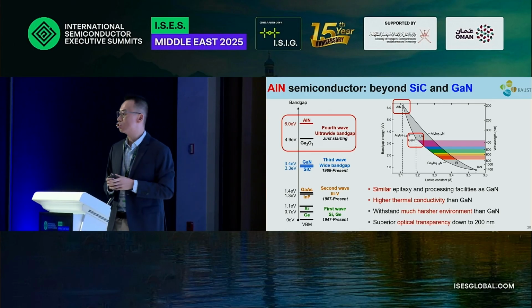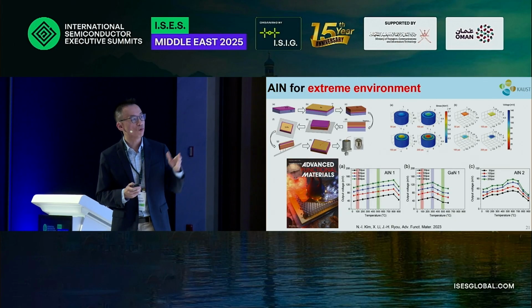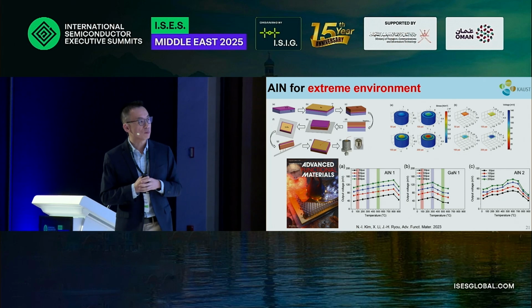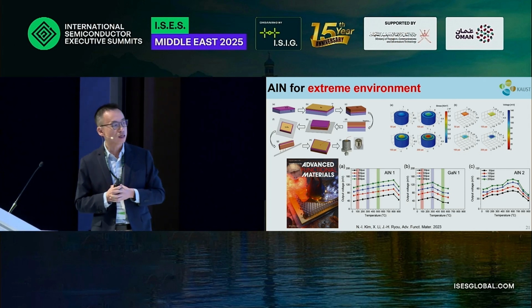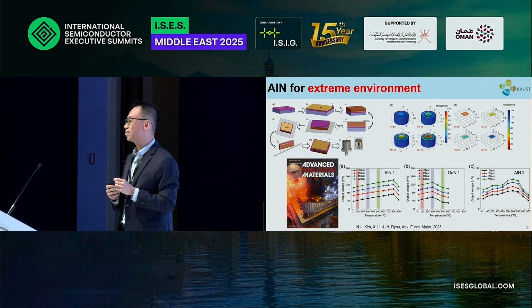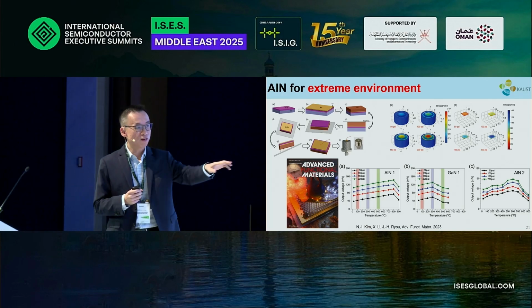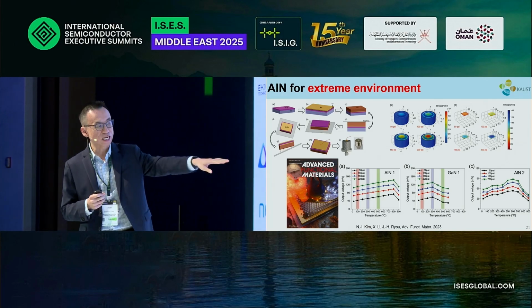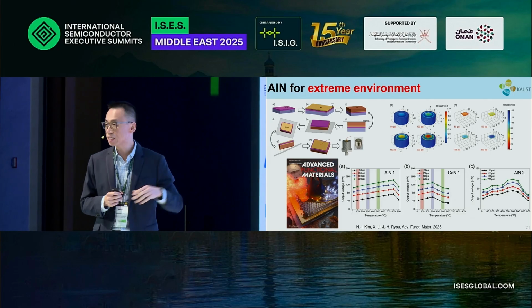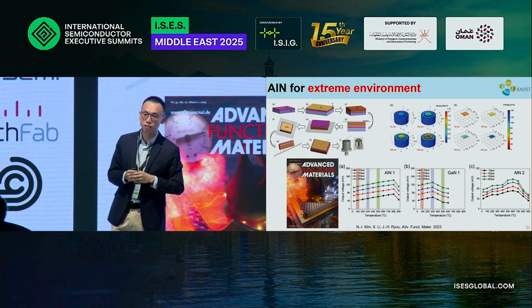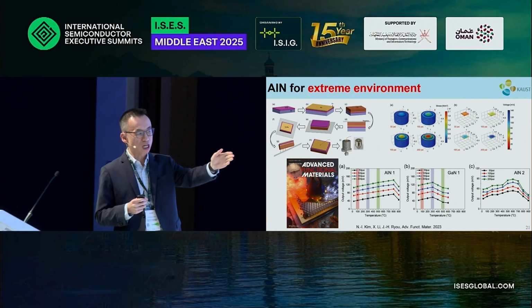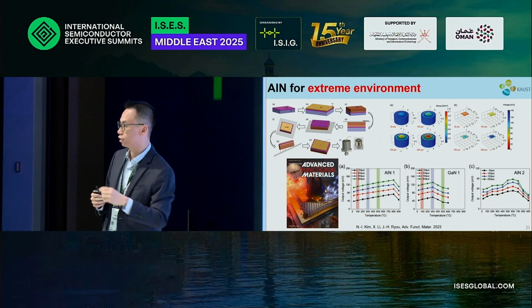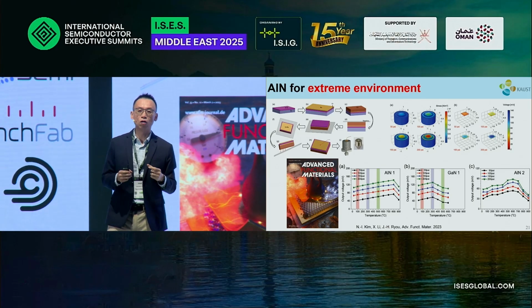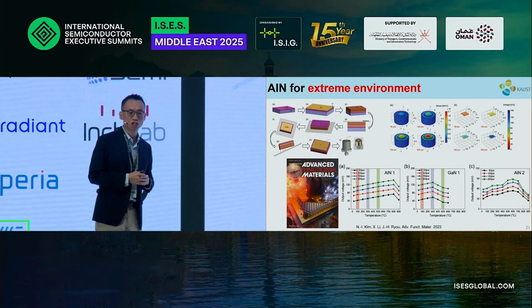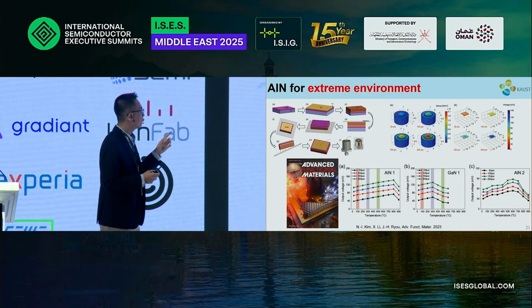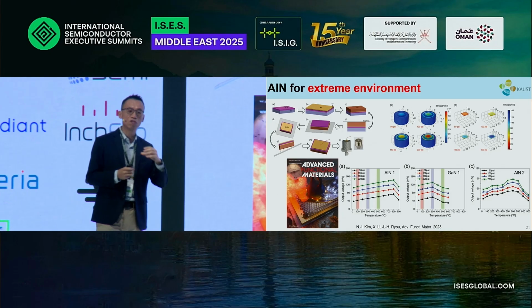Talking about the harsh environment, a couple of years ago we published a work in Advanced Functional Materials where we demonstrated the highest temperature piezoelectric sensor to date. As you can see here, the aluminum nitride sensors developed in our lab can reach a maximum temperature of about 900 degrees Celsius, while gallium nitride will stop at about 600 degrees Celsius because the small bandgap cannot handle the increasing intrinsic carrier concentration at high temperature. So this shows that aluminum nitride can handle very high temperature.